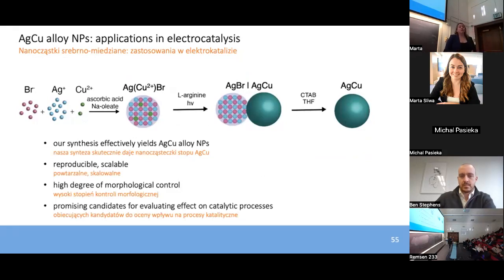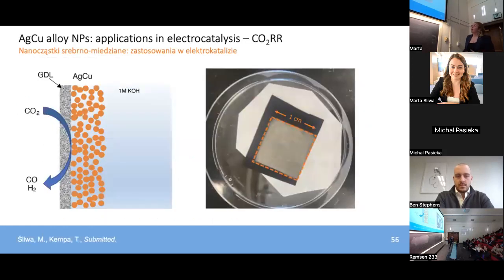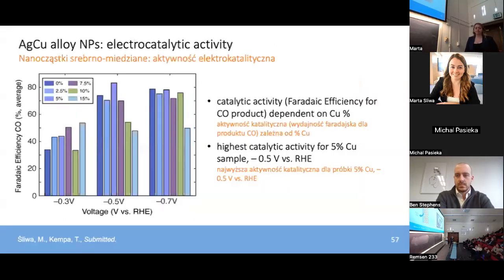That tunable copper percentage incorporation is also exciting, as it could give us a lot of insight into the effect of that compositional change on these electrocatalytic processes. So we wanted to see if we could use silver copper alloy nanoparticles for the CO2 reduction reaction. We evaluated the activity and selectivity of our silver copper alloys by depositing inks of these particles onto a porous, conductive carbon substrate, and in that way forming a gas diffusion electrode, or GDE for short. This setup highly improves mass transport and overall catalytic activity compared to the more commonly seen H-cell configurations in electrocatalytic studies.